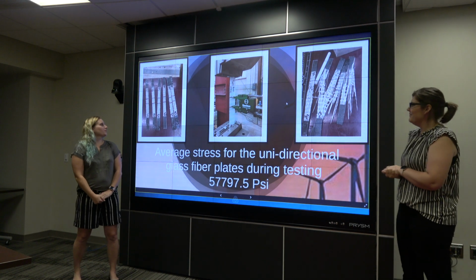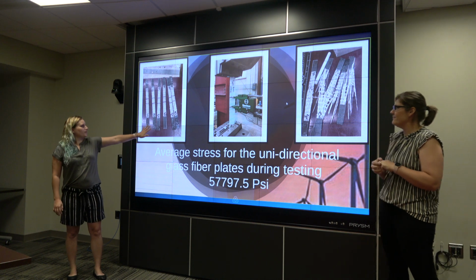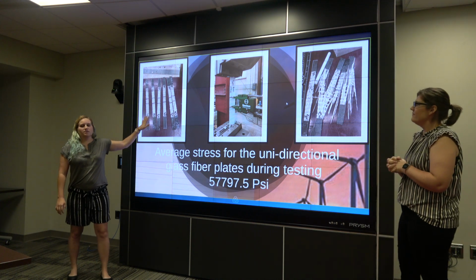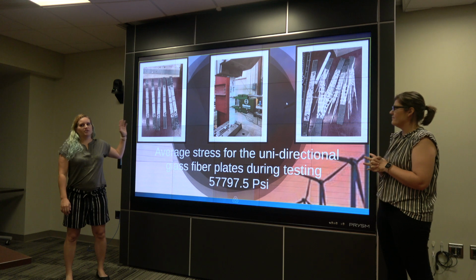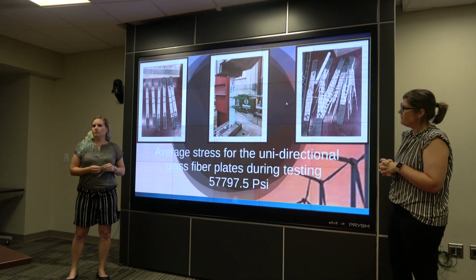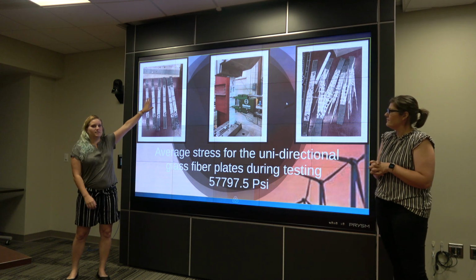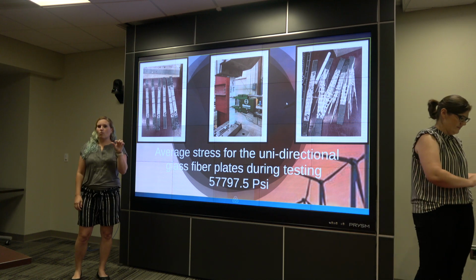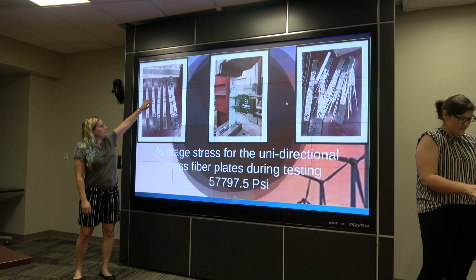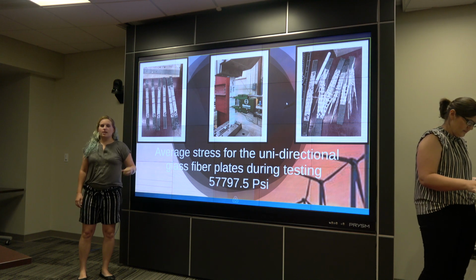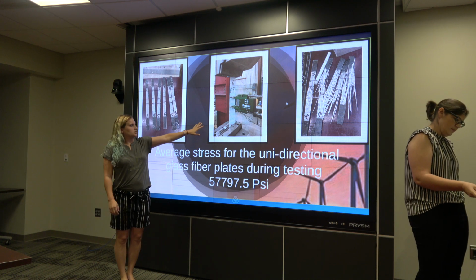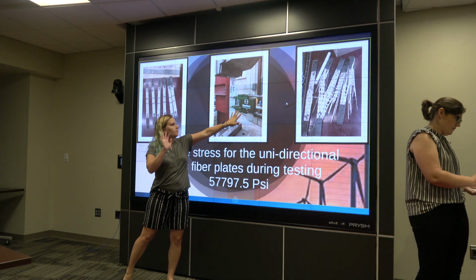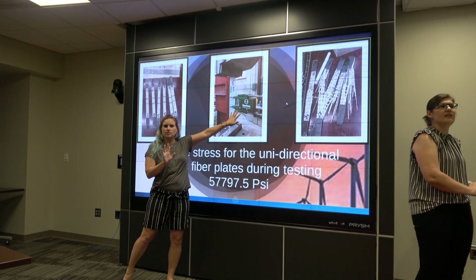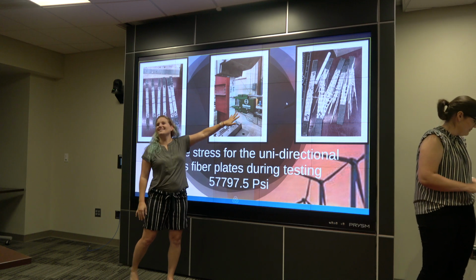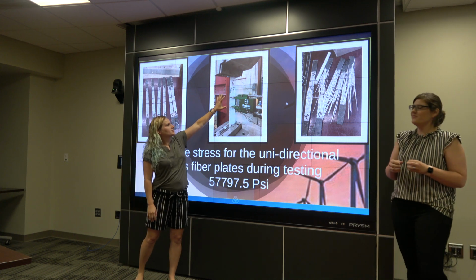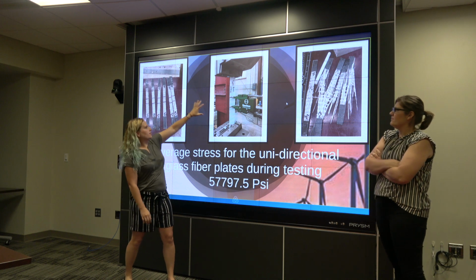So with our machine, the reason why these look like this is because there's the American Society for Testing Materials standards. So these specimens we cut about 15 millimeters wide, about 56 millimeters long, and about 1 millimeter thick. So when we measured off here because we had to measure the area. So when we put it in our MTS machine, we have this right here, and I always forget what this is. Extensometer. Yeah, the extensometer sensor is about 1 inch wide, which is about where these are.